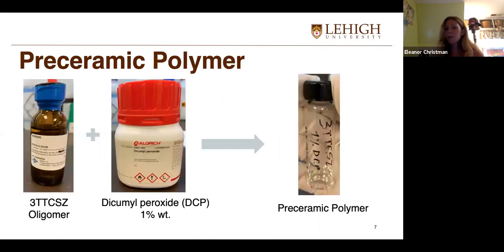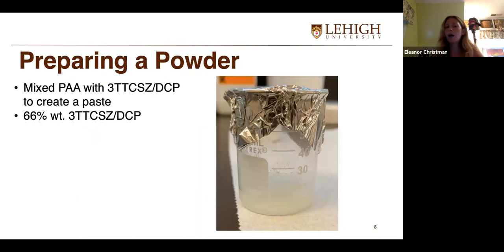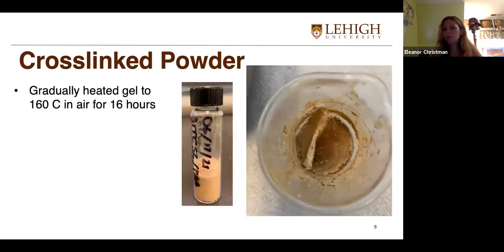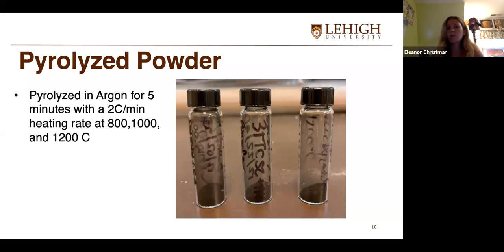And to actually create the preceramic polymer from the oligomer, I mixed the 3-TT-CSZ with dicumyl peroxide, or DCP, at a 1% weight ratio to cross-link it and allow me to make the preceramic polymer. So next, I created a powder where I mixed PAA and 3-TT-CSZ and DCP, which created this paste. And it had a 66% weight ratio. And this allowed me to do some preliminary analysis on this mixture. So I cross-linked this powder by gradually heating it to 160 degrees Celsius in air for 16 hours. And then I pyrolyzed it at 3 different temperatures in argon with a 2 degrees Celsius per minute heating rate.